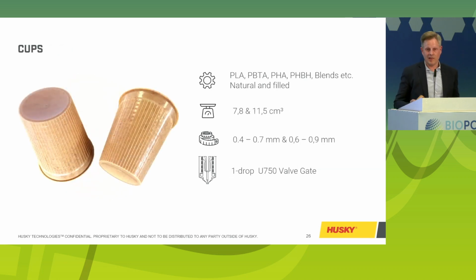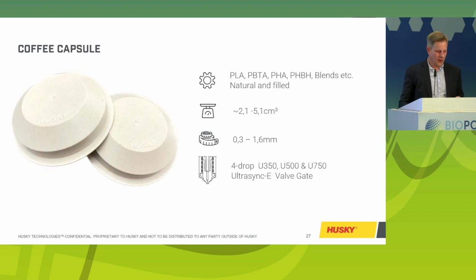Then, addressing the packaging market, a drinking cup, which is known. Here we have 0.4 to 0.7 millimeters of wall thickness, as well as a bigger core or bigger thicknesses of 0.6 to 0.9 millimeters. It's a single cavity system. And as well here we tested different kinds of bioresins. Coffee capsule, this is called the Tassimo design. The Tassimo design is a 4-drop UltraSync E hot runner. As well here we can provide you with different wall thicknesses between 0.3 to 1.6, adjust them individually and do trials as close as possible to your application.